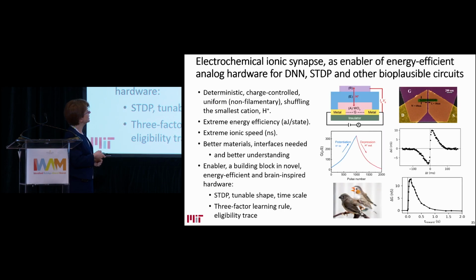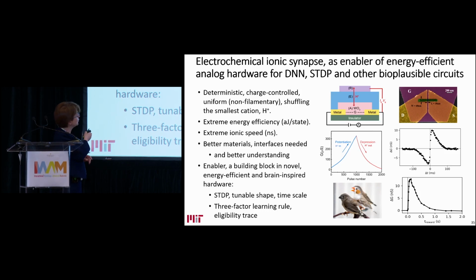Good. So with that, I will end by repeating that these electrochemical battery-like devices, so miniaturized, low-energy, low-capacity battery-like devices, give us the ability to deterministically control the electronic conductivity of a target material. And if you choose the right type of materials, you can scale them down, you can make them CMOS compatible with extremely low energy, and you can push them to very fast speeds. But to be able to achieve both of these with compatible voltages, to integrate them with circuit drivers, you still need a better understanding of these ion conducting, in particular proton conducting, electrolytes and interfaces to push those to become faster.